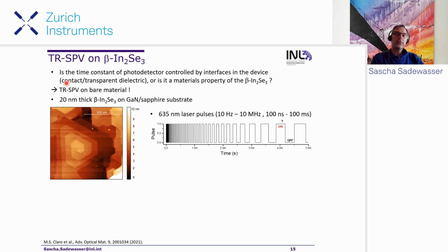So thus, of course, we used time resolved surface photovoltage measurements on the bare material. Here we have the advantage that we do not need to fabricate a full device to measure a photocurrent. We can use the surface photovoltage to measure the time dependence. And we had to transfer the growth onto a gallium nitride covered sapphire wafer. So there's commercially available epitaxial gallium nitride on sapphire to have a conductive back contact and be able to apply the voltage across the layer.